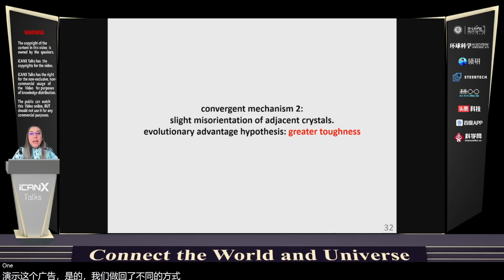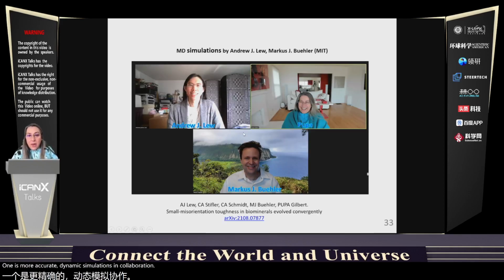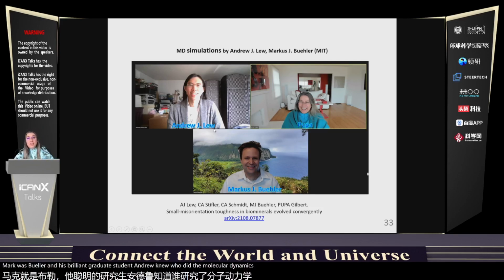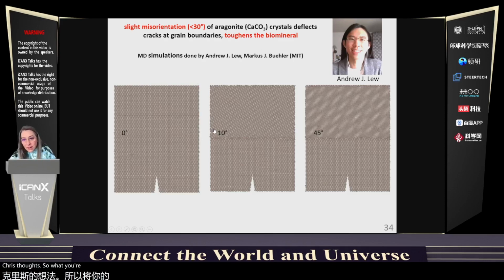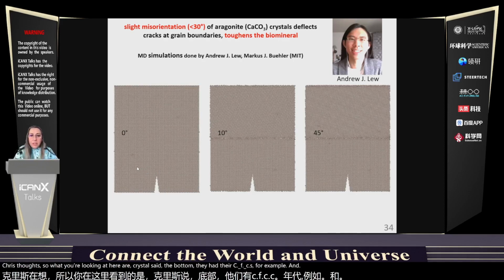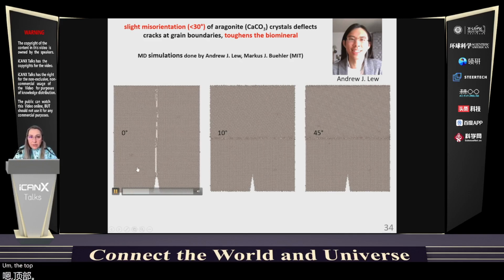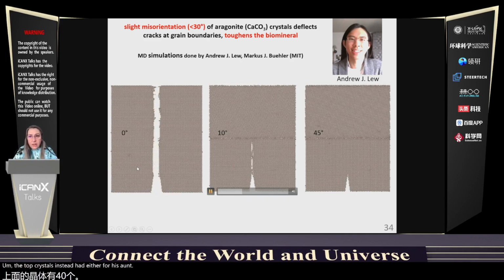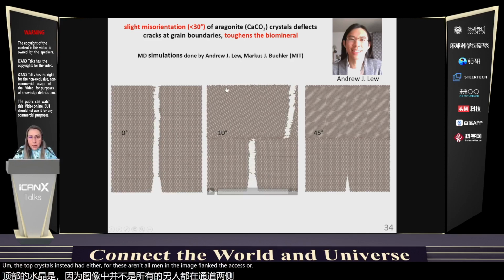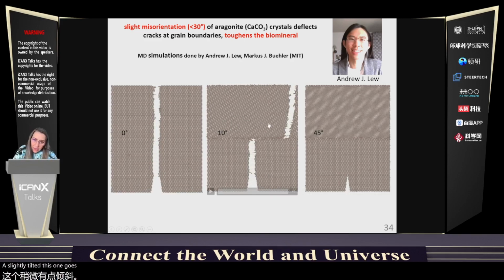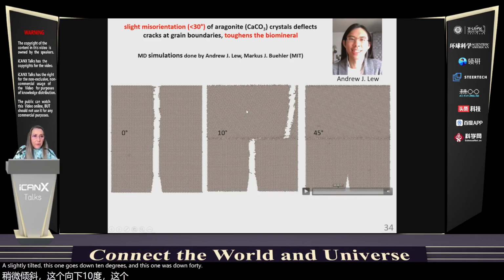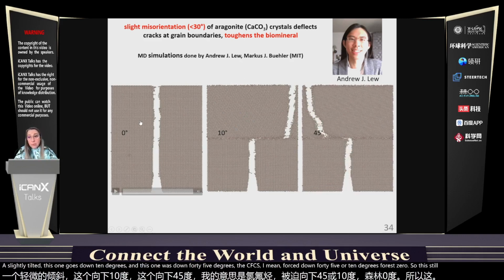One is molecular dynamic simulations in collaboration with Markus Buehler and his brilliant graduate student, Andrew J. Lew, who did molecular dynamic simulations of 2 crystals. So what you're looking at here are crystals at the bottom that had their z-axis horizontal and in the image plane. The top crystals instead have either a horizontal z-axis in the image plane, or slightly tilted. This one goes down 10 degrees and this one goes down 45 degrees. The z-axis, I mean, goes down 45 or 10 degrees or 0. So these 2 crystals are parallel to each other.